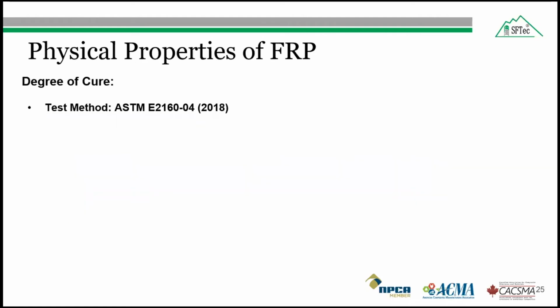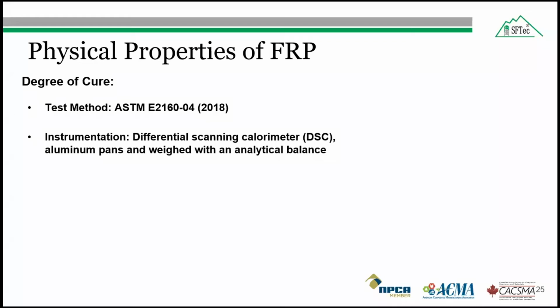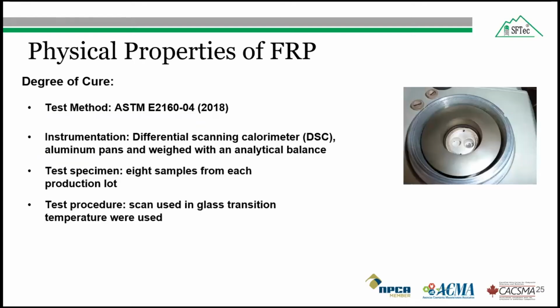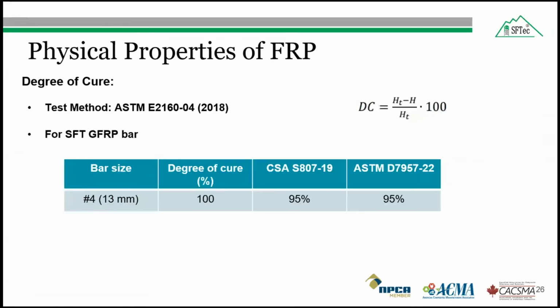The degree of cure is the same. We use the same specimens that we use for the glass transition temperature, but the method is in accordance with ASTM E2160. The instrument, as I told you earlier, is the same as for the glass transition temperature, and the same number of samples is used. The scans used in the degree of cure test method are the same as the scans used for the determination of glass transition temperature. The degree of cure was calculated according to this equation, where dC is the degree of cure, Ht is the total heat of reaction for the sample, and H is the normalized heat of reaction. The value for the SFTec glass fiber reinforced polymer bar number 4 was around 100%, which was greater than the required 95% in ASTM D7957 and CSA S807.